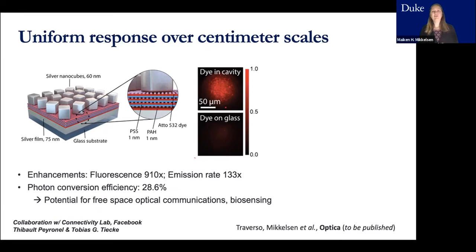And what we found was, after some optimization of these structures, we could actually get a uniform response over centimeter scale areas. In this case, this is not quite to scale. We did increase the density of cubes, but not quite this much. And then we packed in multiple layers of emitters. In this case, we used Atto 532, which is just a common fluorescent dye. We can see that the dye in the cavity is much brighter than the dye on the glass. We had enhancements in the fluorescence of almost 1,000 times, and an emission rate enhancement of 130, but that's really just limited by the instrument response function.